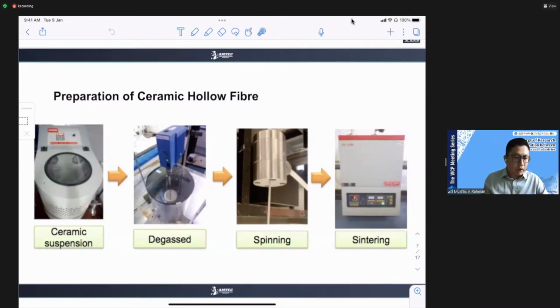As Prof. Hafiz mentioned, we use basic tools to develop our ceramic hollow fiber. We start with producing a ceramic suspension, and this process requires the use of ceramic particles mixed with a polymer binder, organic solvent, and dispersant. We need to mix this using a planetary ball mill.